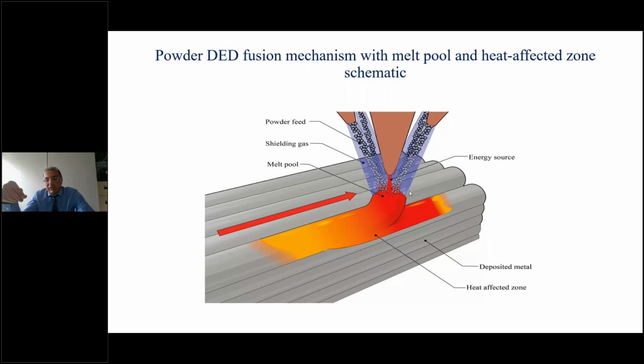With TIG welding, we use a filler wire and melt it with high heat input using a tungsten electrode, or laser welding as well. Very similar, and it creates a melt pool. Here we have powder, but over there we have solid metal which is melted. But again, the process of heat input, solidification, and the defects created are very, very similar.